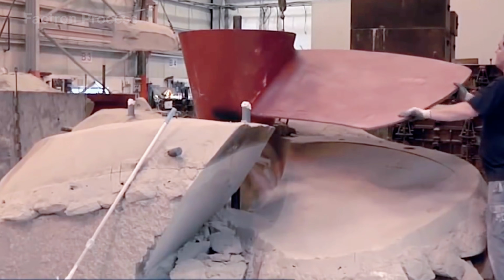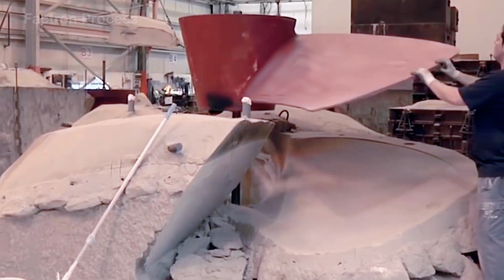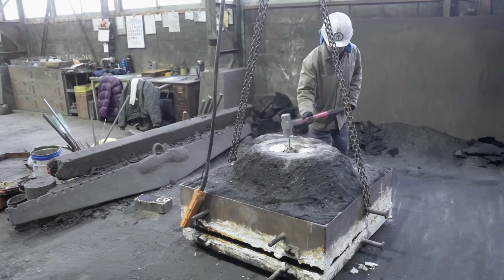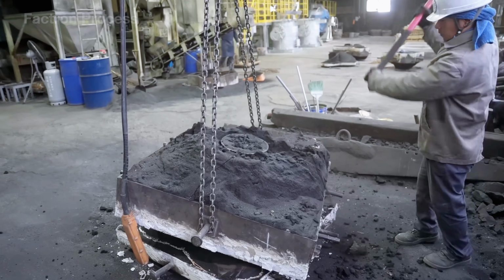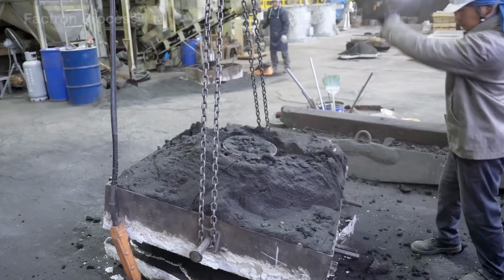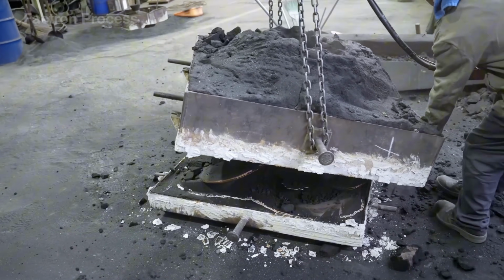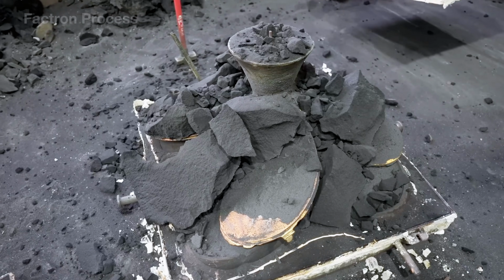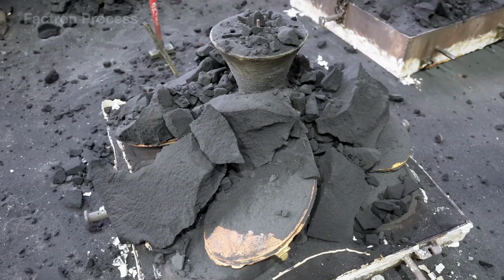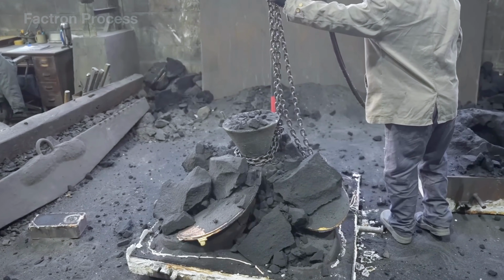Once pouring is complete, the gigantic mold remains inside the casting pit, so the alloy can gradually cool to a safe temperature. For a large propeller, this process may take around 5 to 7 days because the hub, which is several feet thick, always cools much more slowly than the blade edges.